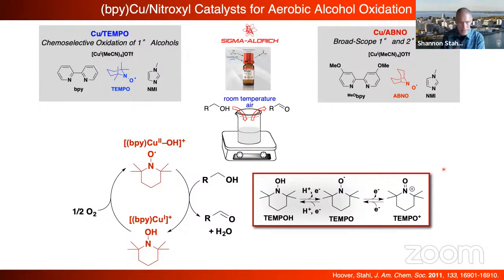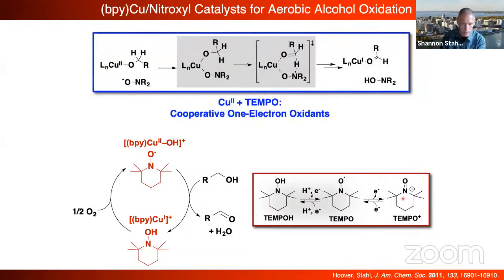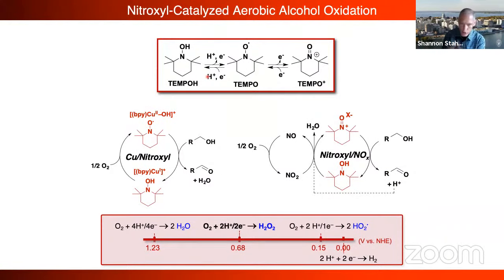But let's come back to mechanism. And so I just want to highlight these three redox states. What I've shown you in this copper TEMPO case is that copper TEMPO is taking advantage of just this low potential redox couple, not the high potential redox couple. Mechanistically, I show that here where you take advantage of the cooperativity of two 1-electron oxidants. Okay, what are the implications of that? Because we've seen two different nitroxyl alcohol oxidation reactions. One that goes hydroxylamine all the way up to oxoammonium in a 2-electron step. The other, which only goes 1 electron to nitroxyl, then takes advantage of copper I/II.